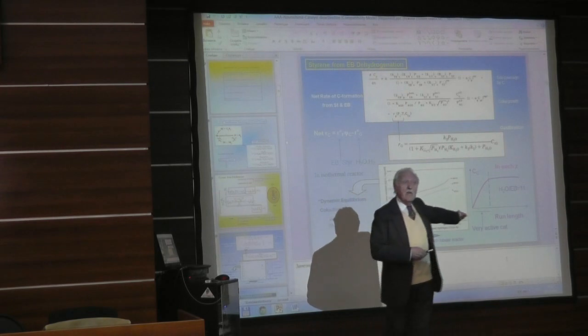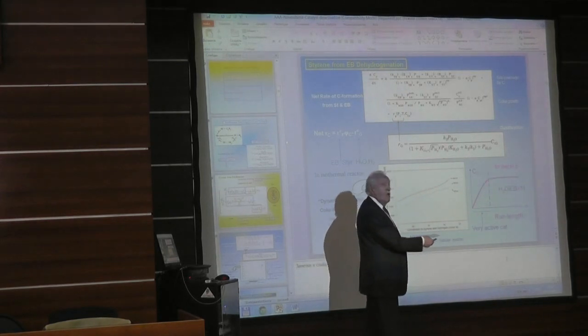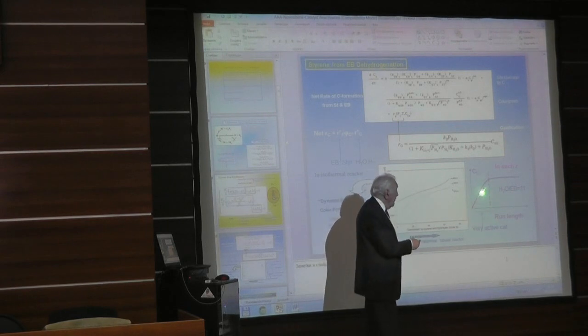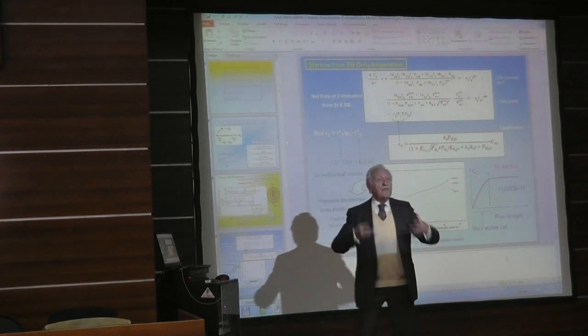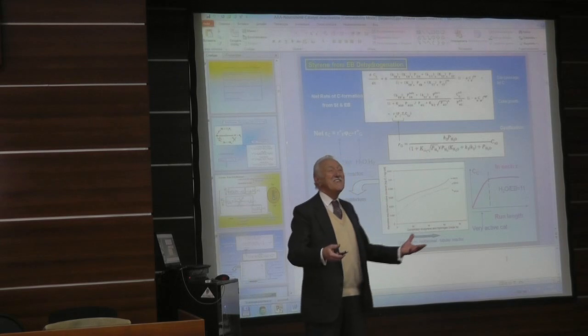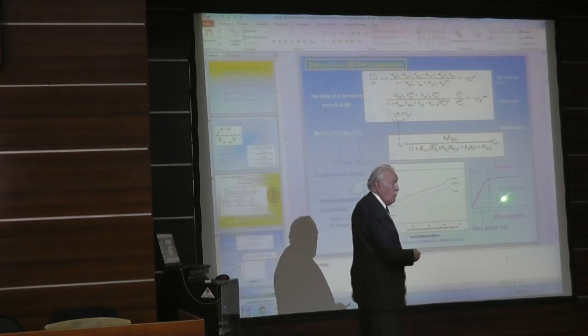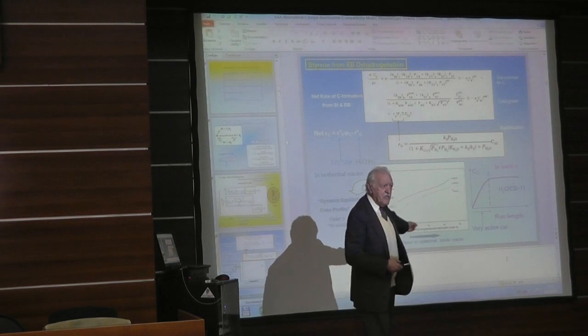Does that mean that if you measure here with your GC and you see, oh, it's constant, I have no deactivation? Forget it, you have deactivated it very much. But you have reached a steady state in the deactivation, and you think it doesn't deactivate. But you're not operating the catalyst at its optimal condition because it's deactivated.